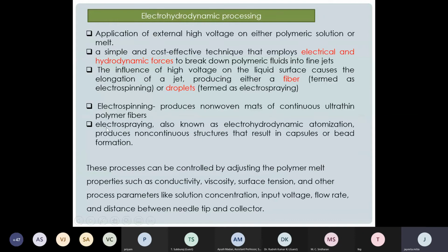Electrospinning produces non-woven mats of continuous ultra-thin polymer fiber, and electrospraying, also known as electrohydrodynamic atomization, produces non-continuous structures that result in capsule or bead formation. These processes can be controlled by adjusting the polymer melt properties such as conductivity, viscosity, surface tension, and other process parameters like solution concentration, input voltage, flow rate, and distance between the needle tip and collector.